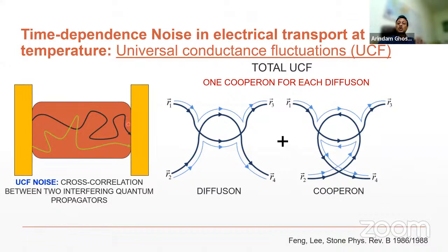So for example, this is one path, this is another path, and these two paths interfere, and this interference can lead to two possibilities. One, the two paths move in the same direction across this region, or the two paths can move in the opposite direction in the same region. So this is only two possibilities. The two interfering paths, if I take a region and they diffuse across it, they can either move in the same direction or they can move in the opposite direction.